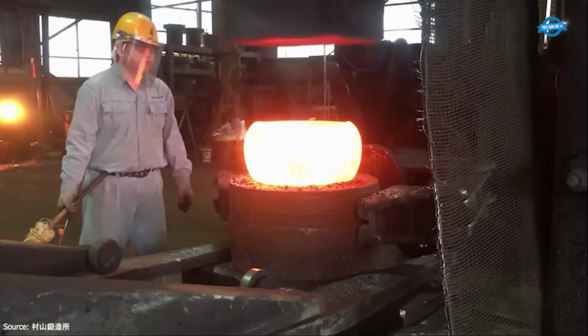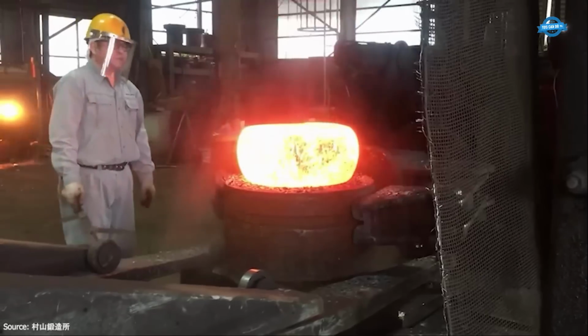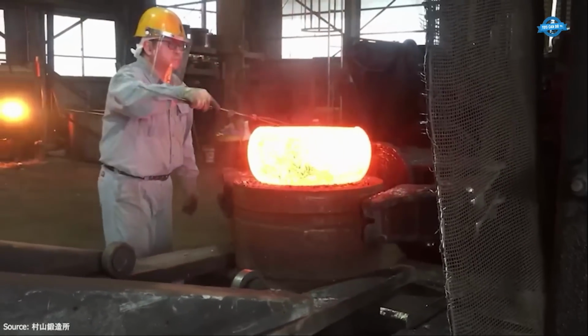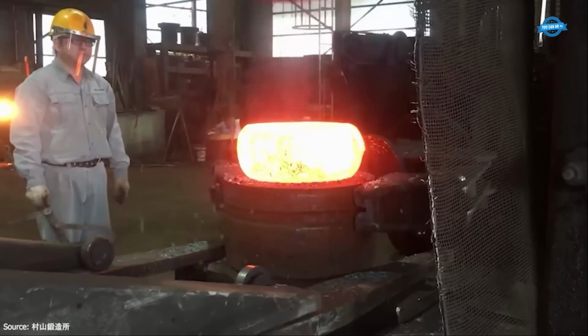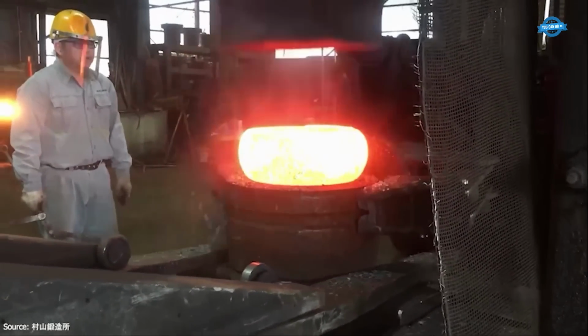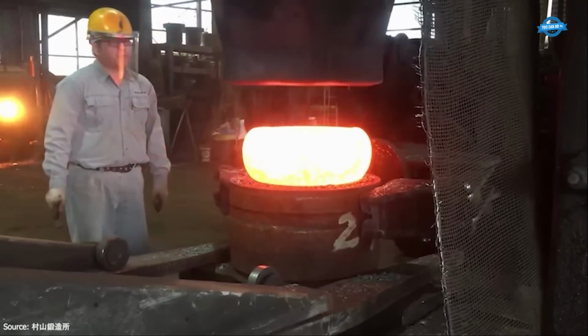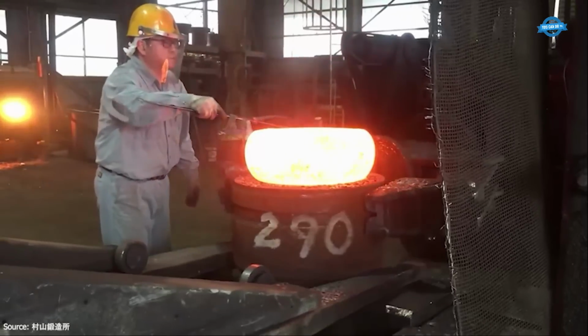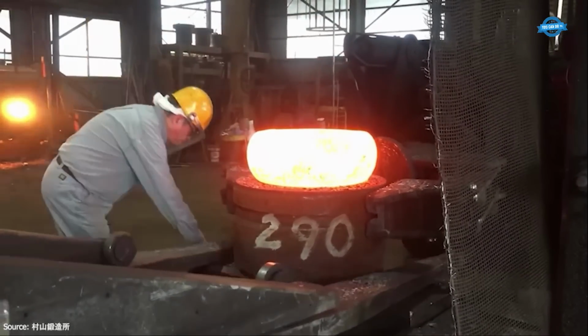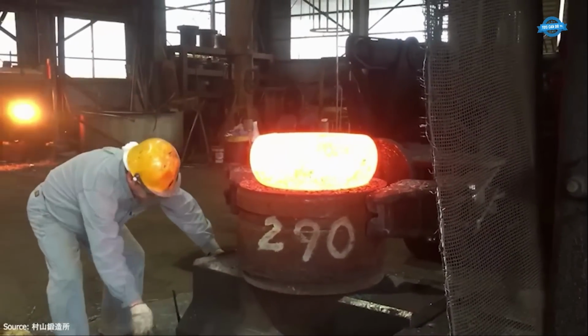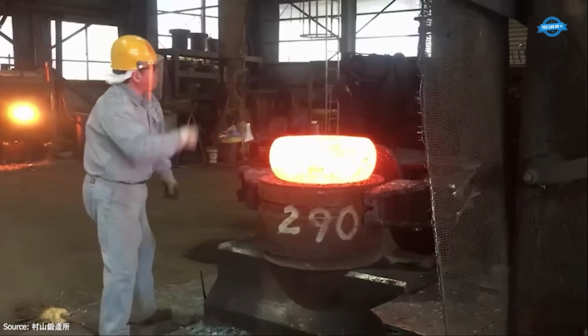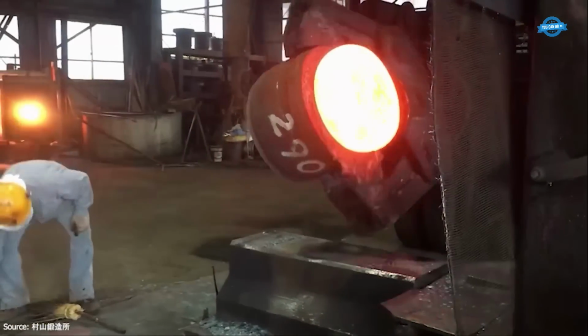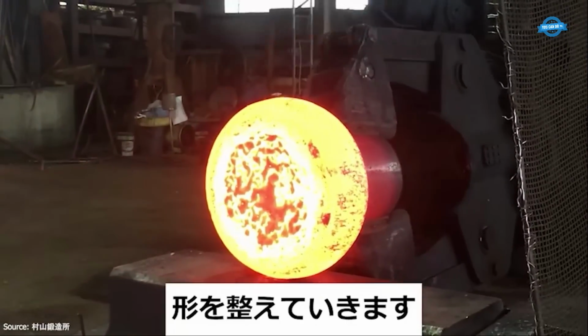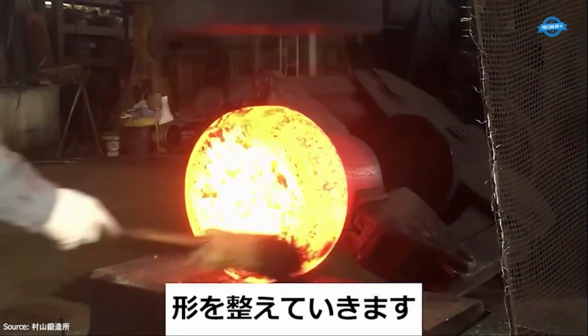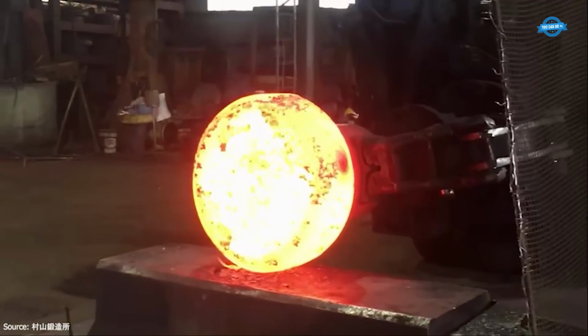The billet is placed on a large, open-die hydraulic forging press, typically operating with forces exceeding 2,000 to 5,000 tons, depending on billet size and material. The operator carefully positions the billet under the press and executes controlled deformation strokes. The initial pressing flattens and spreads the billet to establish basic proportions. Skilled rotation and repositioning are essential to ensure even material flow, avoiding weak points or anisotropic grain structures.